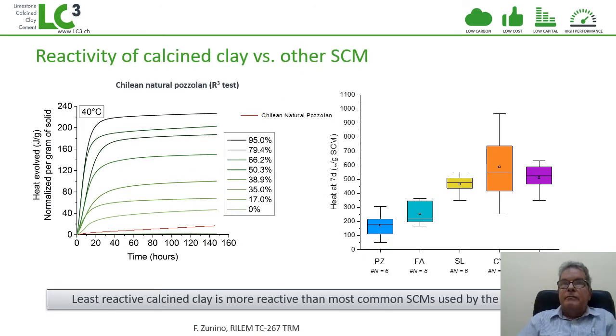Clays are very interesting. People are always concerned by the fact that you have to calcine them and spend some energy, but you realize here, if you compare clays with different pozzolans like fly ash, slag, and silica fume, that even the lowest grade clay has a higher reactivity than any of the other pozzolans that we're dealing with. Meaning, if we're able to get a reasonably reactive calcined clay, we are way beyond any of the other materials we have considered so far as supplementary cementitious materials.